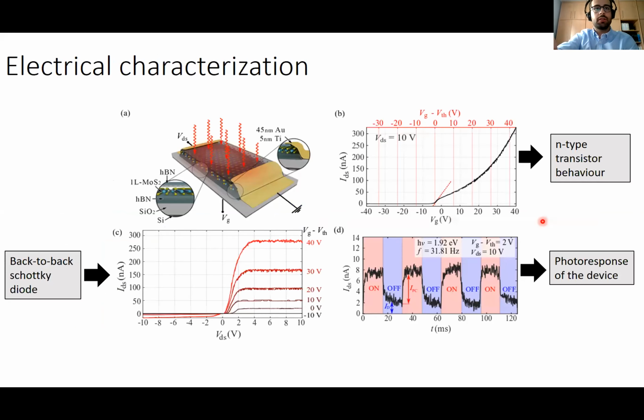we start our measurements by characterizing the electrical response of the device. Here in figure A, we have a representation of our device, and we have marked here the two-terminal electrical configuration of the measurements. In this zoom, we have the geometry of the contacts, which are edge contacts made of titanium and gold. And here in this zoom we have the structure of the two-dimensional phototransistor.